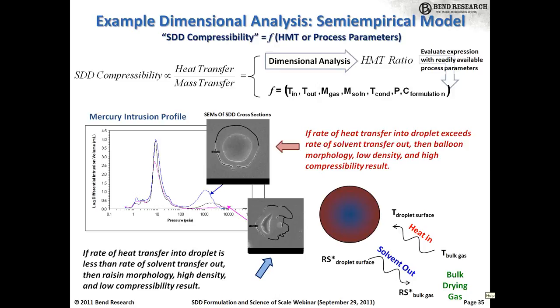And that resulted in a dimensionless number that we call the HMT ratio that can be evaluated at the readily available process parameters. So the process parameters we've been discussing: the inlet temperature, outlet temperature, gas feed rate and solution feed rate, and condenser temperature. And then you also need to take into account a couple of constants that are specific to the formulation.